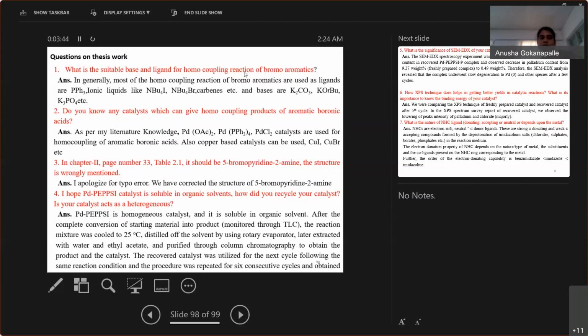Do you know any catalyst which can give homocoupling product of aromatic boronic acid? As per my literature knowledge, palladium acetate, palladium triphenyl phosphine, and palladium chloride catalysts are used for the homocoupling of aromatic boronic acid, and copper based catalysts are also used for homocoupling of aromatic boronic acids.